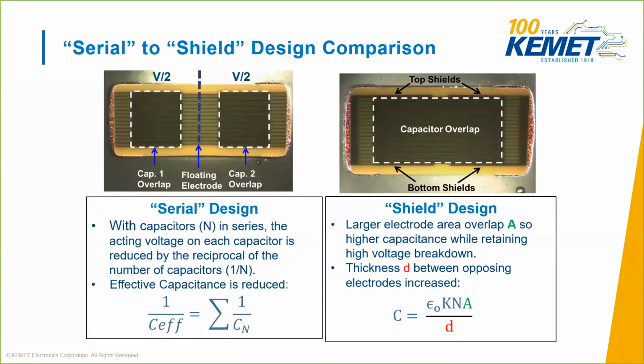Now, the shield design has a much larger overlap area, and there's no lowering of the capacitance, so the standard capacitance equation, as we saw before, still applies. Since there's no lowering of active working voltage in this area, the thickness of the electrodes, so the opposing electrodes, has to be increased for higher voltage breakdown capability. Now, even though this lowers the capacitance for a given X7R system, the capacitance can be increased up to 4 times more than a serial electrode design. Now, to address flex crack concerns, KEMET has developed an ArcShield series with flexible termination technology.